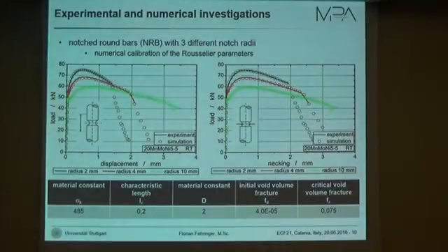Second step is the numerical calibration of the Rousselier parameters. We used notched round tensile bars with in total 3 different notch radii: a 10 millimeter notch radius, a 4 millimeter notch radius, and a 2 millimeter notch radius. As you can see with the Rousselier parameters down here, we are very well able to describe not only the elastic plastic behavior of the material, but also the crack initiation and the failure behavior. On the left, you can see the load displacement behavior for elongation of the specimen, and on the right-hand side we have the load over necking, the reduction of diameter in the notch.